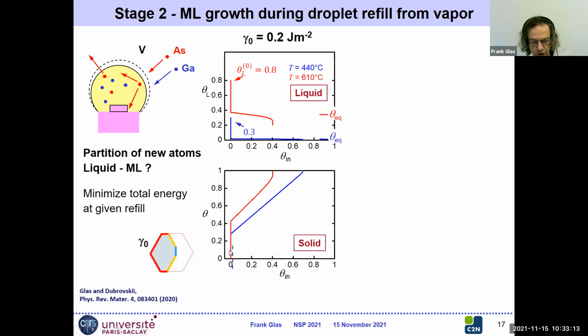So at a low temperature, you see that you have the initial growth from what was, so here I must say that I chose arbitrarily the content of the droplet at nucleation. So we form a monolayer, and then the coverage grows more or less linearly. At higher temperature, it's also the case, except at the end, the coverage accelerates. So what does it mean? If we look at the liquid now,